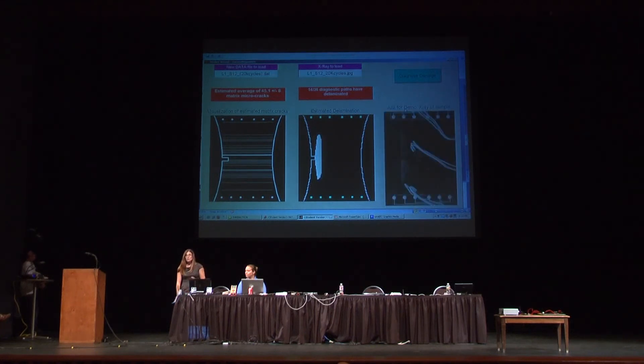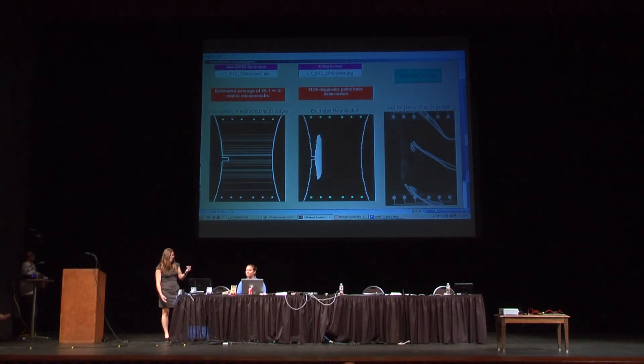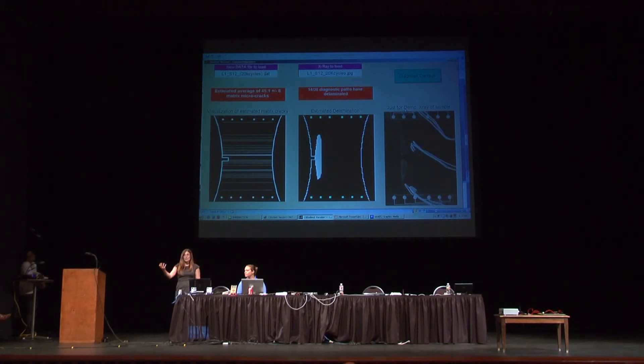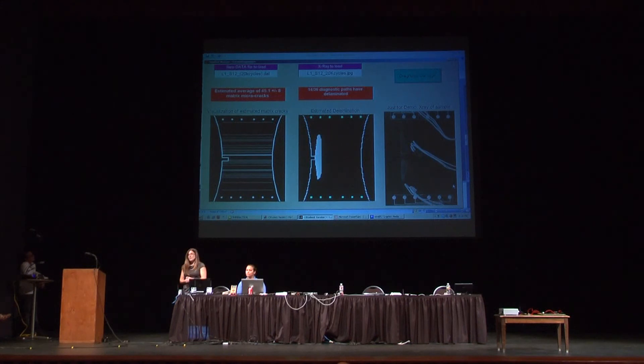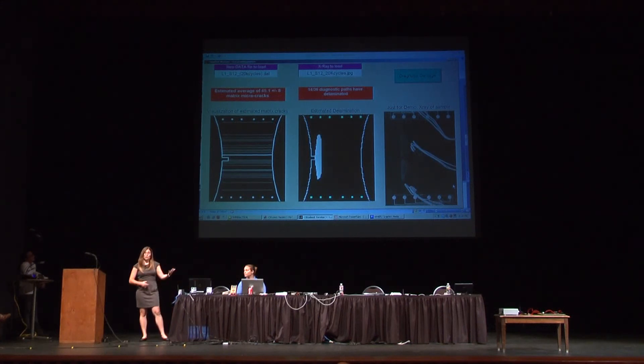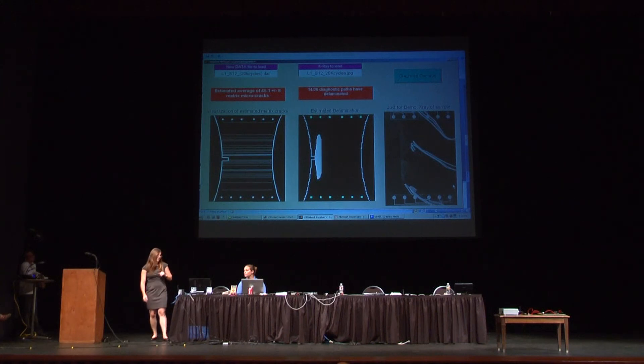Using a diagnostic technique that I'm still developing, it gives you an extent of the delamination, visualized here in the white areas. As the third step, just for this demonstration, I asked Colleen to take an X-ray of the sample so you can compare yourselves the estimation versus the real damage. The white areas here are the delamination, and the horizontal white lines are the matrix cracks present. As you can see, this is very real time — I actually had to pause the software so that I could explain it to you.